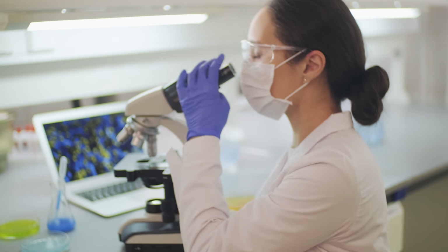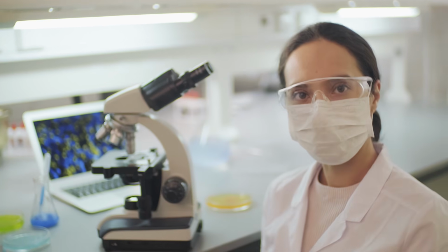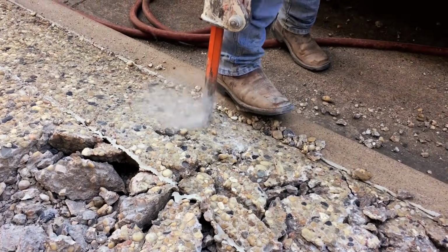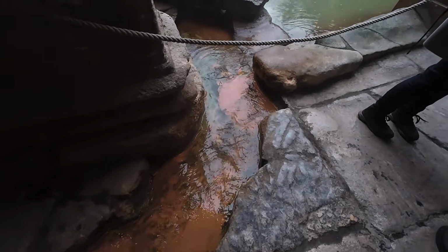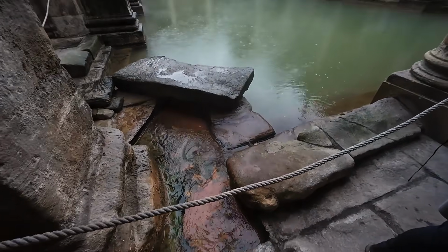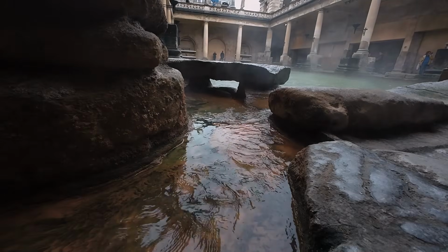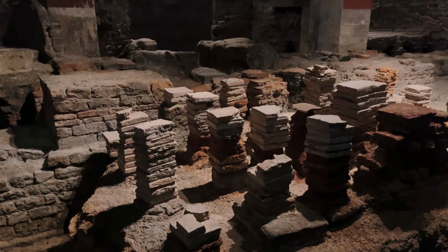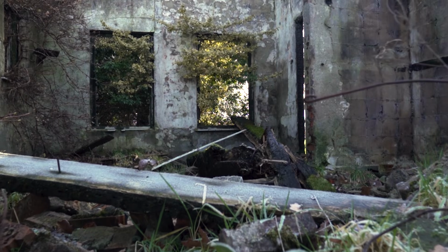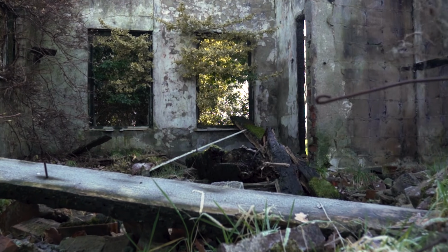In laboratory experiments designed to replicate the Roman formula, researchers intentionally cracked samples of this hot mixed concrete and allowed water to flow through the fractures. Within 2 weeks, the cracks had sealed themselves. Water could no longer pass through the material. Concrete made without the quicklime clasts never healed and remained permanently damaged.